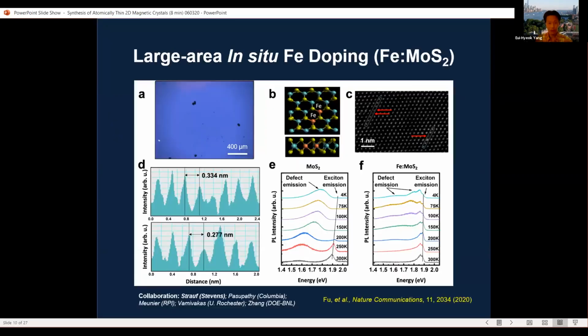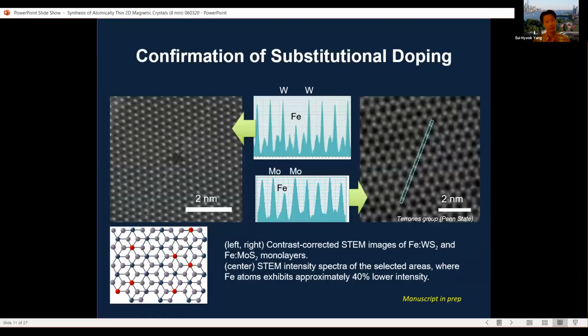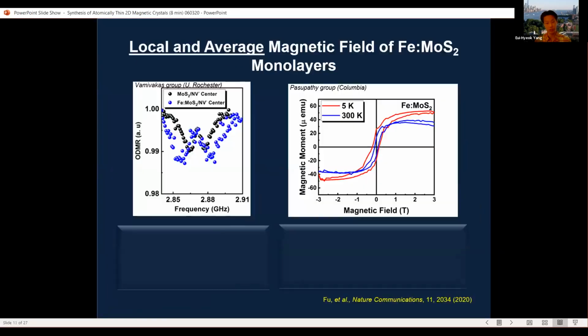It is also important to confirm the substitutional doping. If you have interstitial doping or adhesion of these nanoparticles of these ions, basically it's not going to work when you fabricate devices, right? So it is important that you have substitutional doping. We confirm this using contrast corrected STEM images of iron doped molybdenum sulfide as well as tungsten sulfide here. Basically, we compare the intensity spectra based on the atomic numbers and so on, and we can very precisely determine the doping site. Of course, we have also performed other measurements in addition to this, which I don't show here.